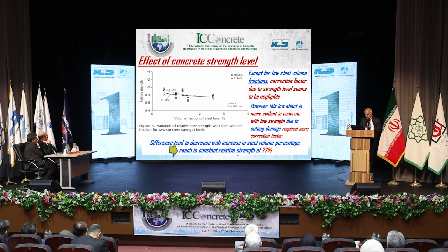But at this part, however, this effect is more pronounced for low strength concrete because of the cutting damage, as you expected. As the strength is increased, it seems that the relative strength for different volume fractions is getting constant, to nearly 77%.